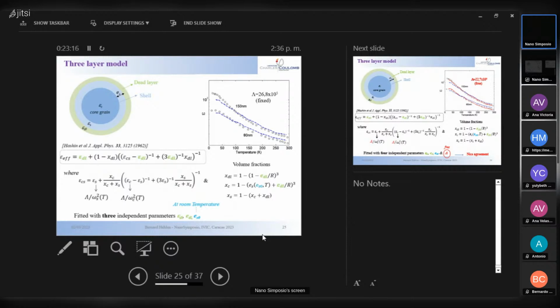This is quite a heavy formula, but here we know many things by experiment. And so in this formula, there are only 3 independent parameters: the permittivity of the dead layer, the thickness of the dead layer, and the thickness of the shell at room temperature. Those are the only 3 parameters. All the other parameters are given by the experiment.